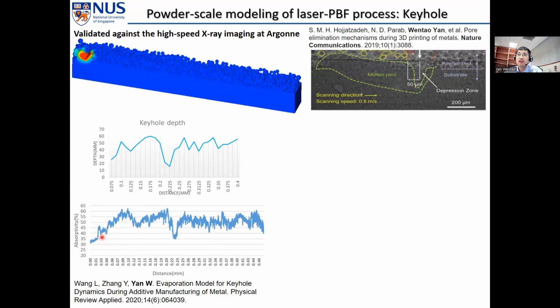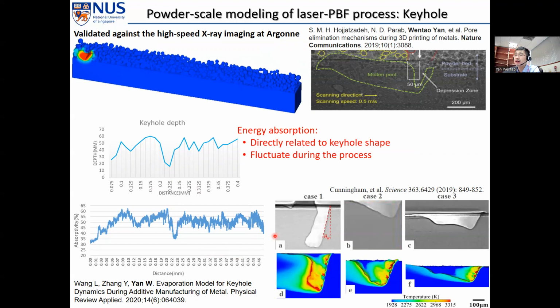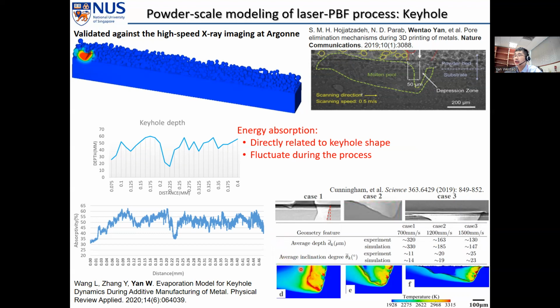You can see the energy absorptivity at different locations is fluctuating all the time because it is directly related to the keyhole shape. When the keyhole is shallow, the energy absorptivity is low because there are fewer laser reflections. When the keyhole depth is larger, the energy absorptivity becomes larger because there are more reflections within the keyhole. Even for the same laser power and same powder bed, with different scan speed, or the same scan speed with different power, the energy absorptivity can be different.